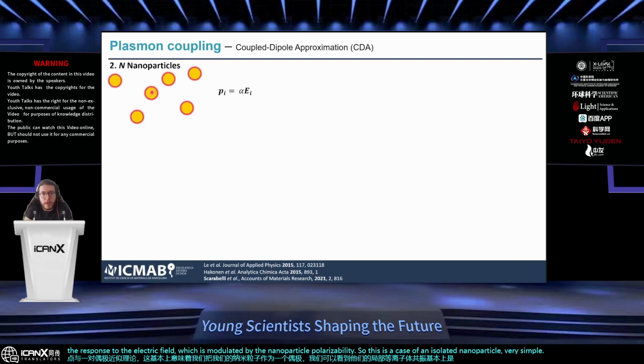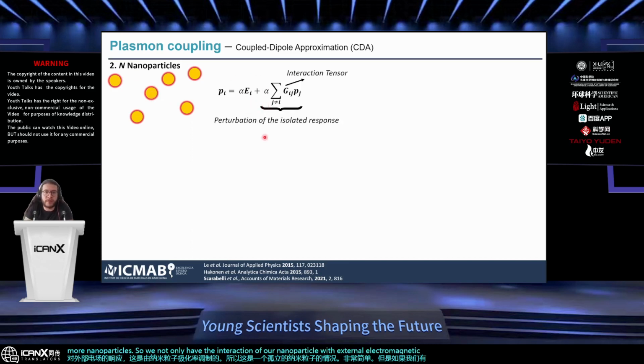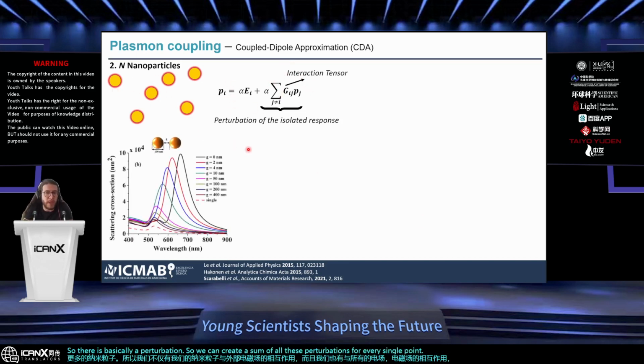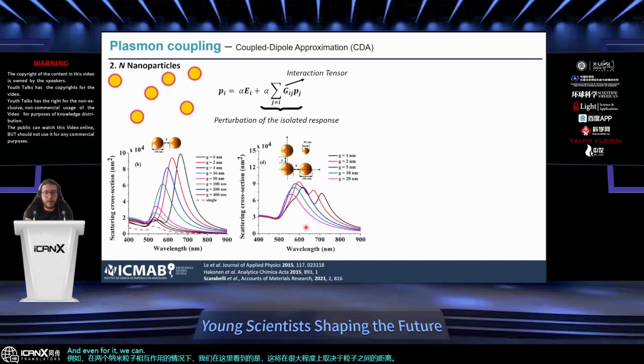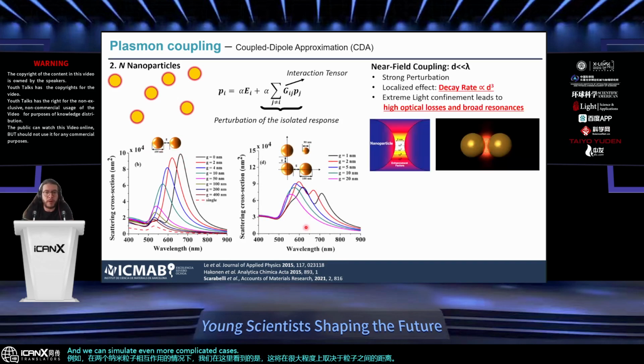But what happens if we have more nanoparticles? So we not only have the interaction of our nanoparticle with the external electromagnetic field, but we also have an interaction with the electromagnetic field of the other particles. So there is basically a perturbation. We can do a sum of all these perturbations for every single particle in the system, and we can simulate all this. And what we see here, for example, in the case of two nanoparticles interacting with each other, is that this will strongly depend on the distance between the particles.